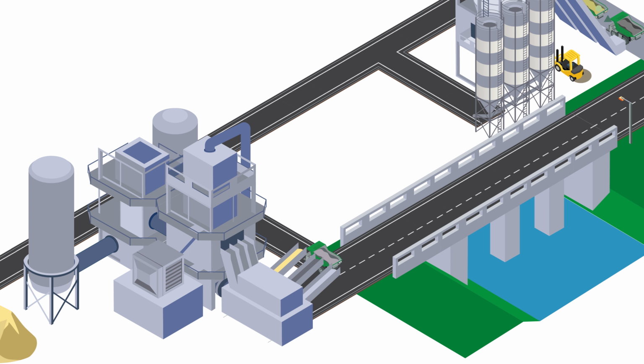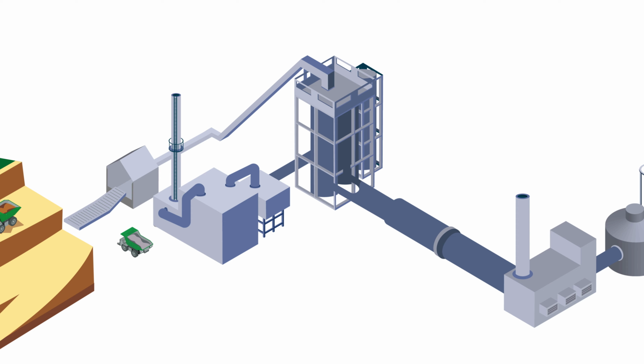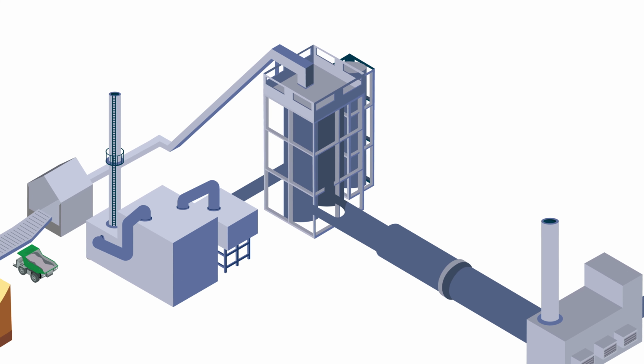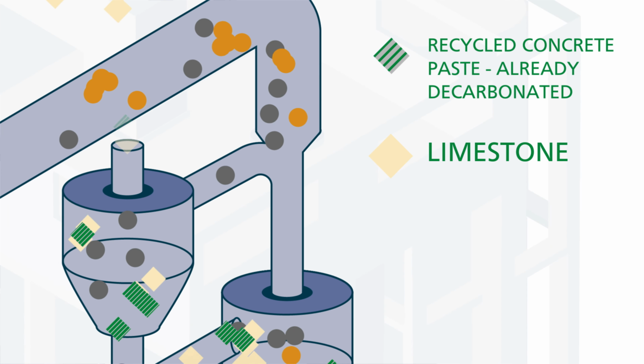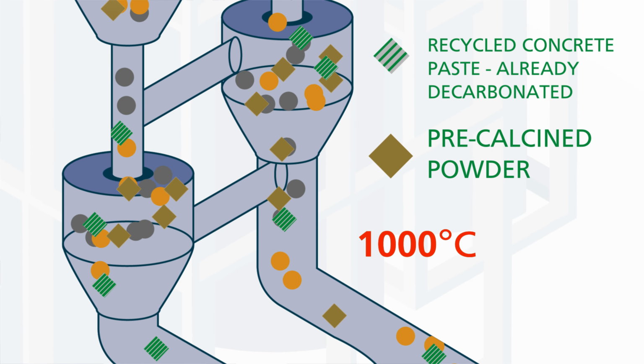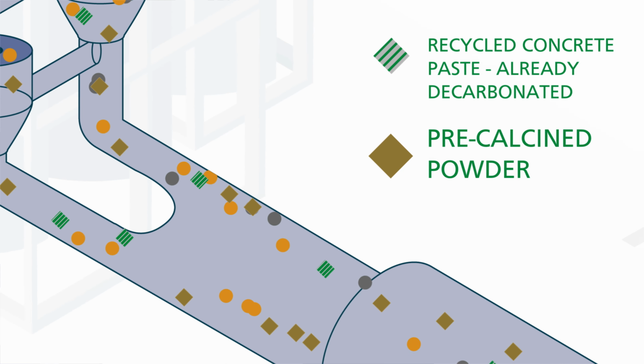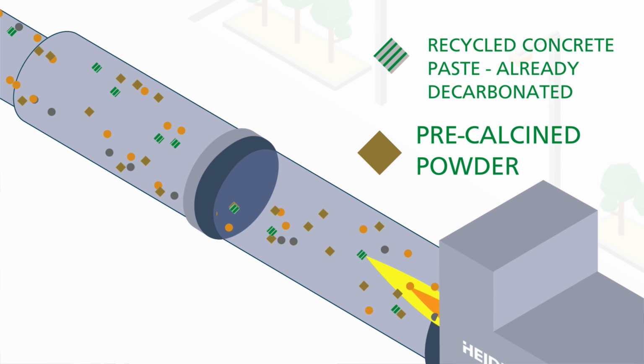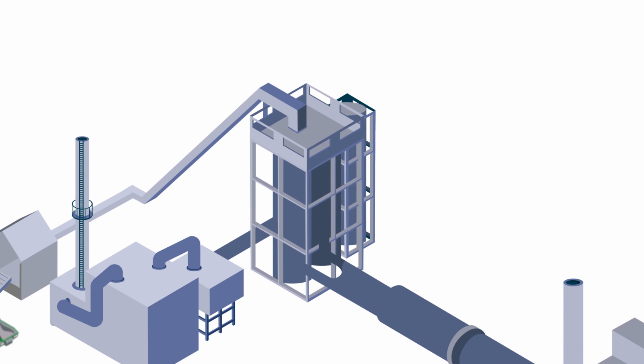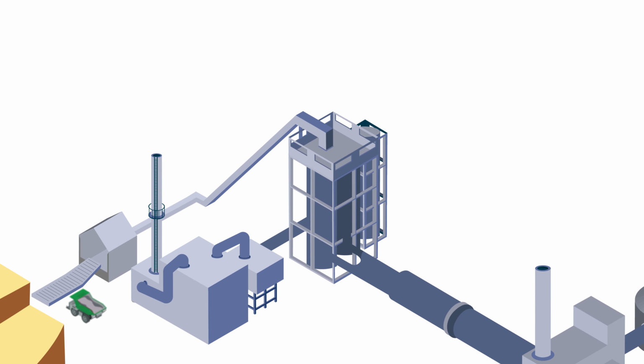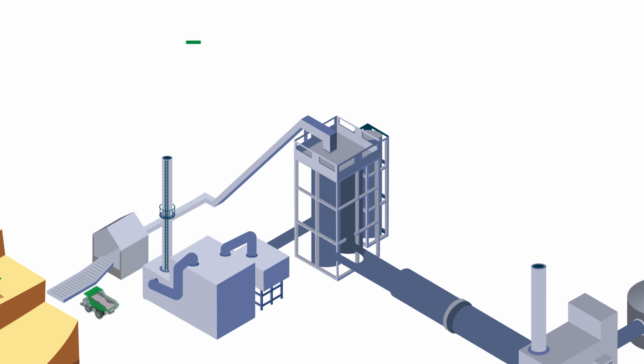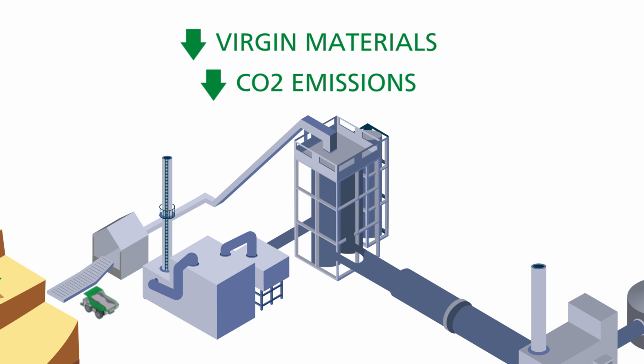The recycled concrete paste can be used in 2 ways. On the one hand, it can be directly utilised and replace part of the limestone in the raw meal for clinker production. Compared to the virgin material limestone, the calcium oxide in the RCP is 80% CO2 free. In this way, the use of the recycled paste as a limestone substitute not only reduces the need for virgin materials, but it provides low CO2 clinker.